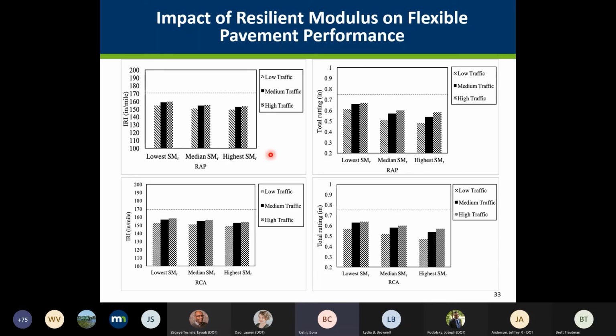I would say the current model that we use is not fully covering that, because this was, I think, the last version. It is somewhat covering it, but not fully. I think it needs more improvement. Yeah, the freeze-thaw effect on the RCA materials. I don't think it has a model; the pavement ME has a model that varies these resilient modulus values with freeze-thaw conditions. But I don't think it takes this cement content into effect as we would like to see, as it is really happening in the field.